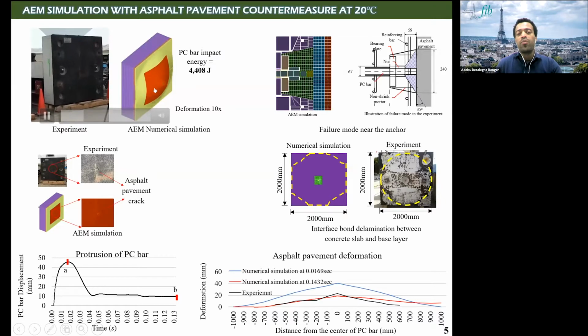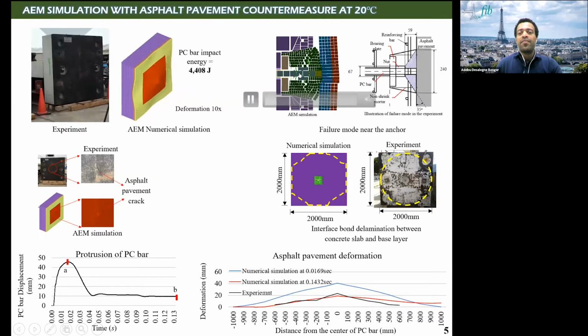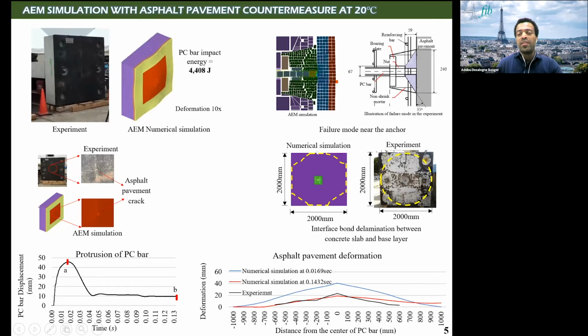This is how the pavement is deformed, actually 10 times magnified. This is the failure mode near the anchor, and this is an illustration of the failure mode in the experiment. The stress originating from the head of the nut in a diagonal shape creates a cone-shaped crack in the mortar. When the bar is pushing forward, interface bond delamination was observed like this one. In the numerical simulation, the area inside the yellow marker is where the bond was lost. This is the experiment. So you can see the pavement has bond delamination. It means the pavement deformed over this wide area, so it can consume more energy. And we also observed a minor crack around the center of the PC bar, like this one. You can see very few cracks.